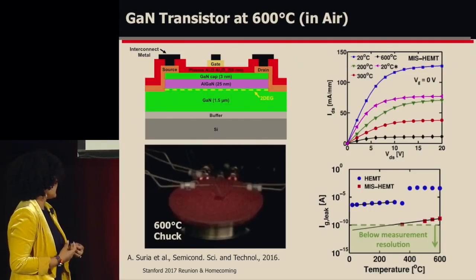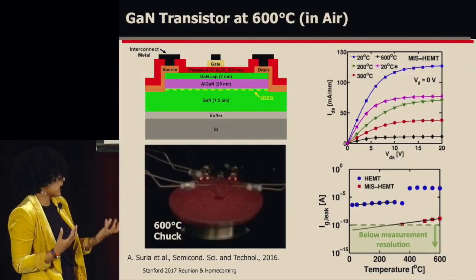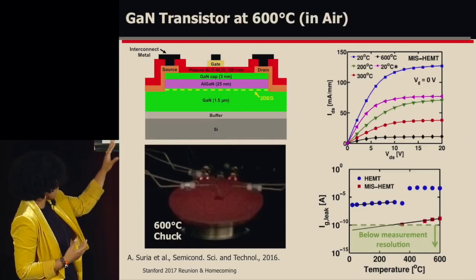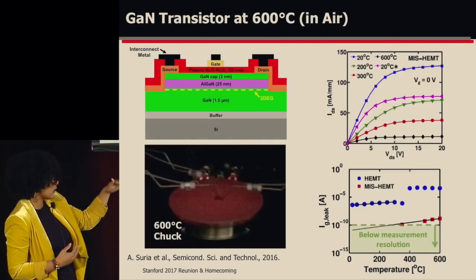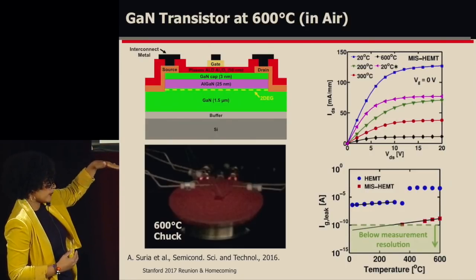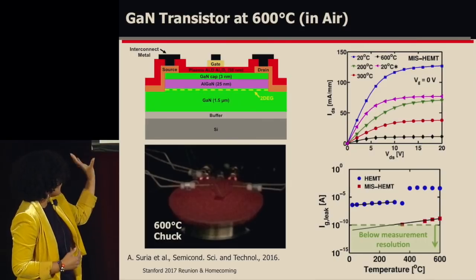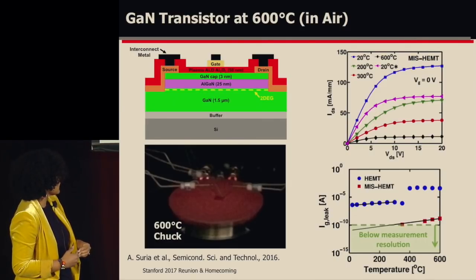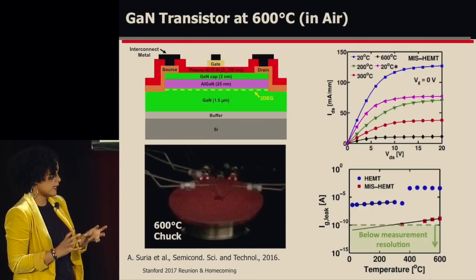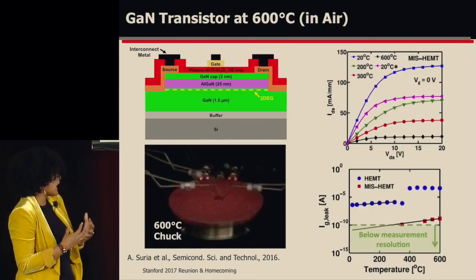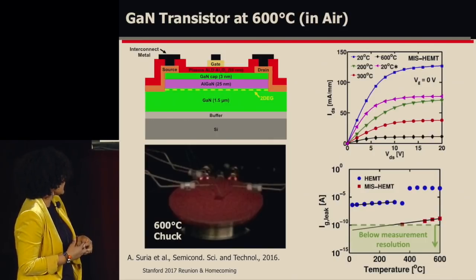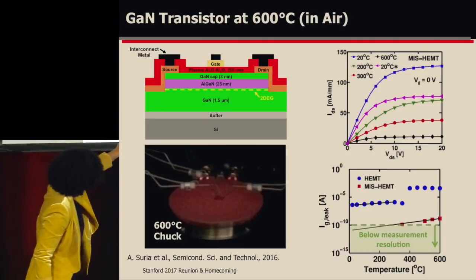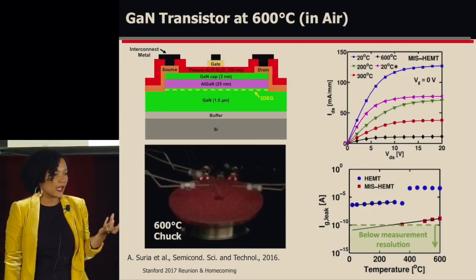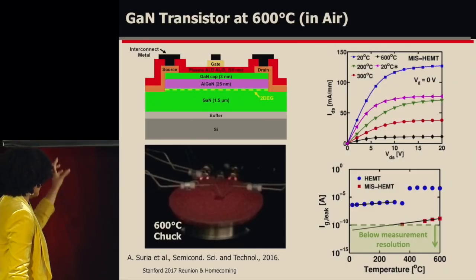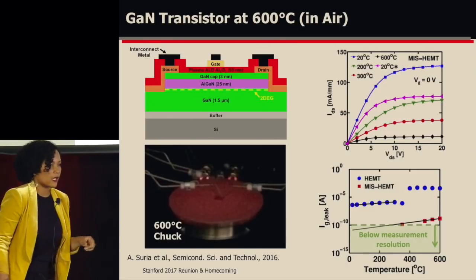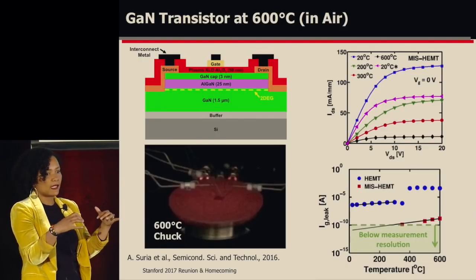So we have adapted the gallium nitride platform to create high-temperature electronics. This is a cross-section of the electronic structure. We use silicon wafers. We do a lot of work to develop the buffer structure to be able to grow the device layer gallium nitride films. We also have shown that atomic layer deposited dielectrics help them work better at elevated temperatures. Unfortunately, it's a little hard to see, but this is a picture of a glowing chuck at 600 degrees Celsius. We have our gallium nitride chip on top of the chuck, and we're probing it, and we're actually able to get electronic signals.